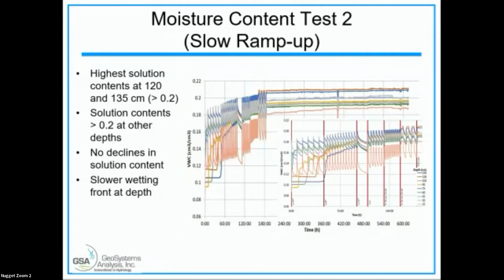Now, this is the classic theory. This is what you would expect based on consolidation permeability testing. The most pressure is down at the bottom of the column. And that's where you would expect for the ore to have the greatest density, and that's going to result in a higher moisture content at an equivalent irrigation rate. We saw no declines in the solution content, just kind of a steady rise, and then slower wetting front at depth. And also, okay, next slide.